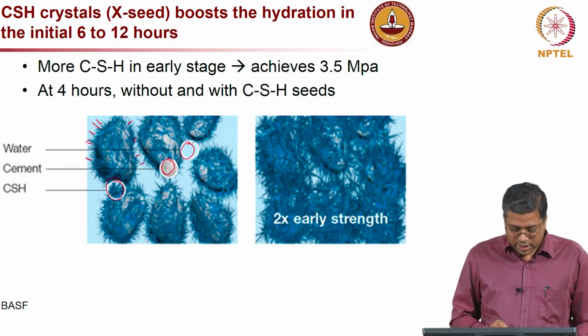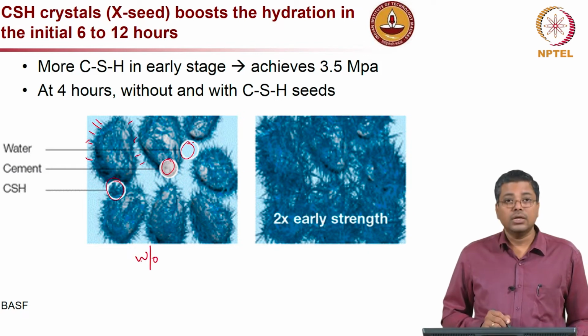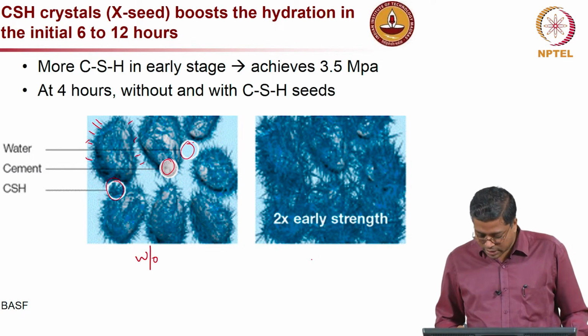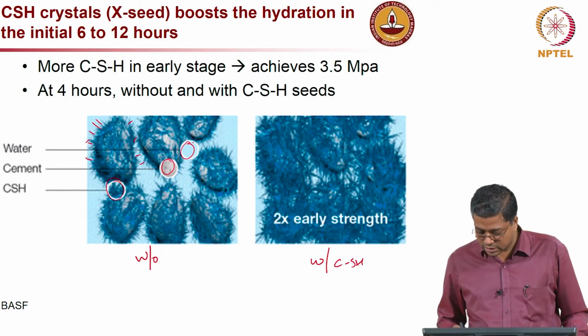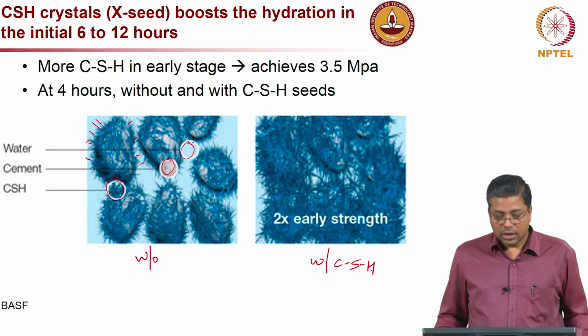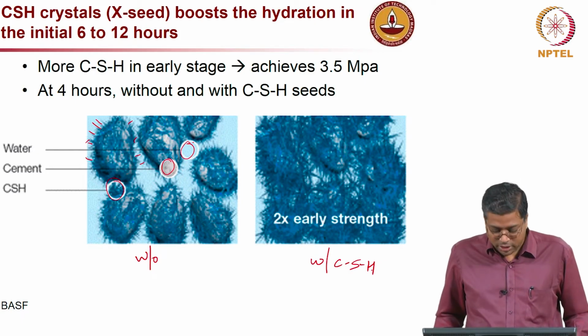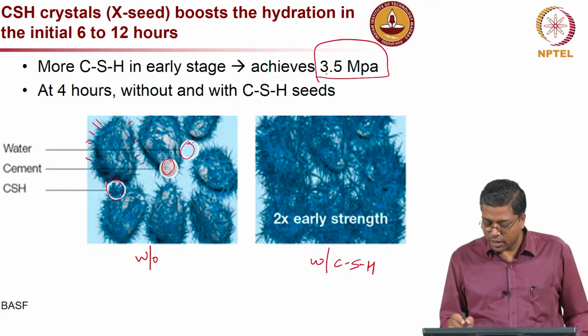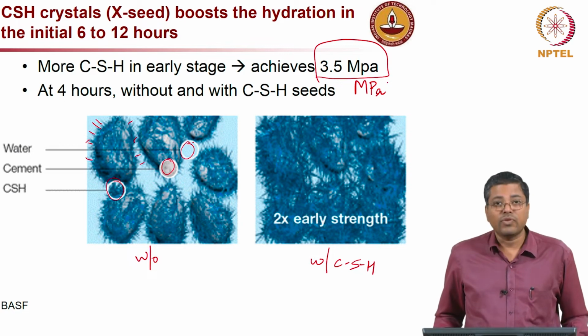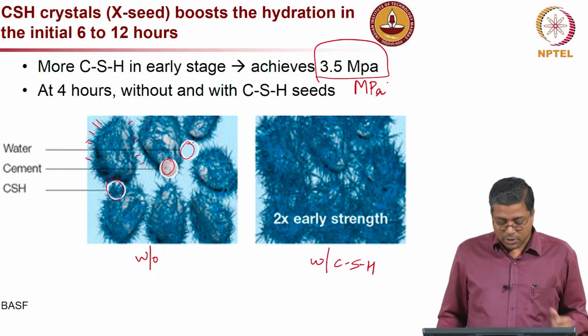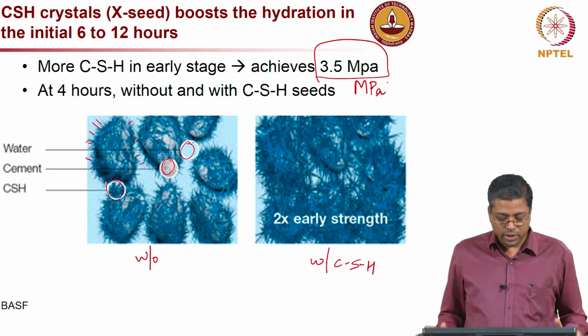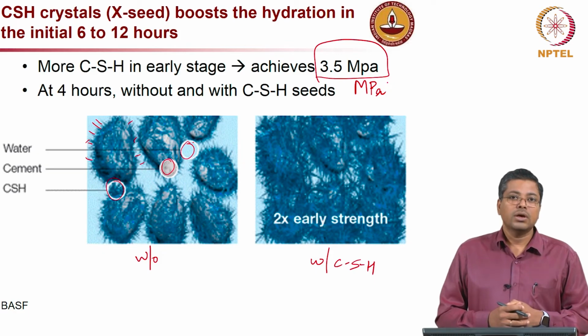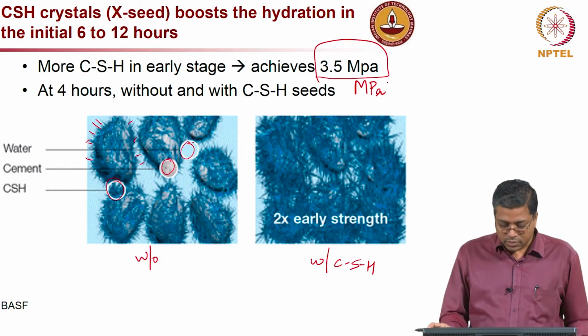Here the picture on the left side is without the CSH seeds, whereas this is with CSH seed. Okay. Now, this will help in gaining the early strength and reaching this 3.5 MPa. Let me correct this, this is capital MPa. Okay. So, that 3.5 MPa strength criteria is achieved, especially for cold weather climates. This is very helpful, because these seeds provide the nucleation point for the cement hydration. That is the technology. Okay.